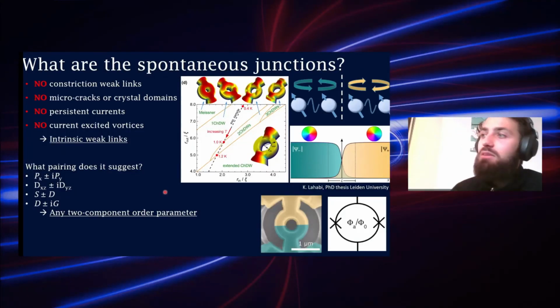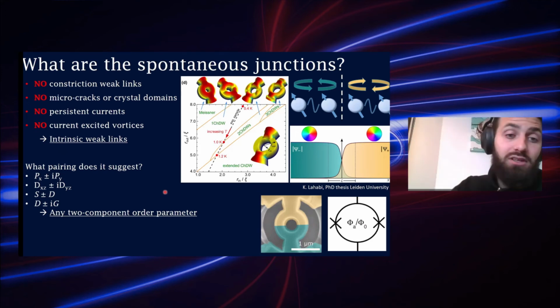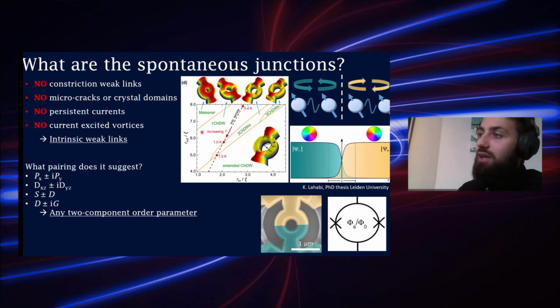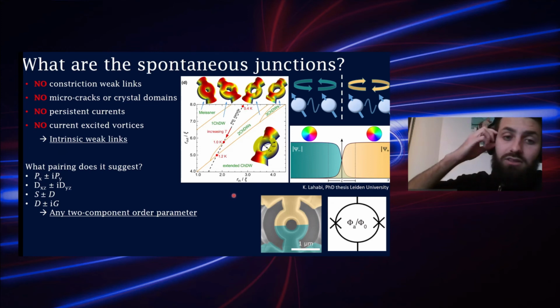This depends a bit on the temperature, and according to the simulations, for the chiral p-wave state, it depends on temperature and the dimensions of the ring. In this figure, you see the inner and outer radius normalized to the coherence length.